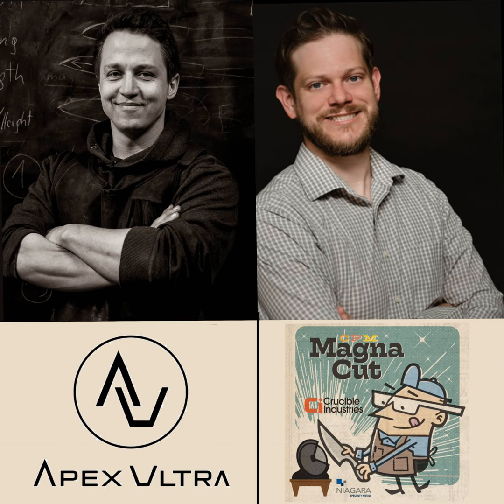So we cast this, I think it was 10 kilos of an ingot, of which we could use like 3 or 4 kilos. And then I just basically threw it in the forge and tried to simulate the process of forging and hot rolling the steel into a bar. And then we made a bunch of different testings of heat treatments and characterized those again with Larrin's testing method to see how it would compare to all the other steels that he has been testing in the past.